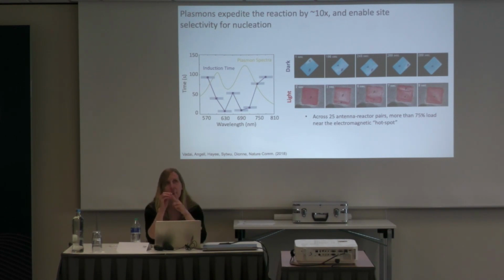And then another thing that's happening is, because you have this increased electromagnetic absorption, you can have increased rates of transitions of light from the HOMO to the LUMO in that hybrid palladium-hydrogen orbital. So there's both direct electron transfer that can give rise to hydrogen formation in the environment in this case, or you can also have increased rates of transitions that come from the increased local density of optical states.